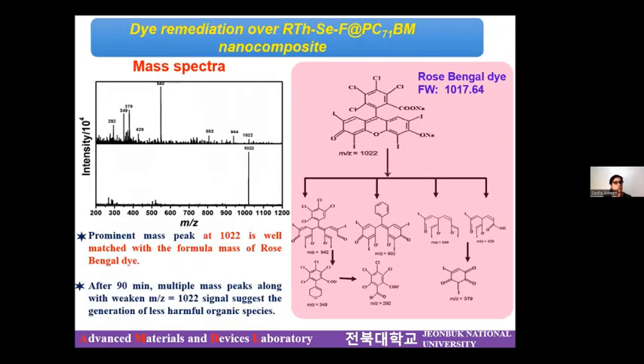Since we wanted to confirm that it is simply not a procedure of absorption, that's why we have performed mass spectroscopy. Here, this peak obtained at the position of 1022 corresponds to the formula mass of the Rose Bengal dye. However, after the photocatalytic experiment, this peak has split into several small peaks, and these small peaks actually correspond to the intermediates.